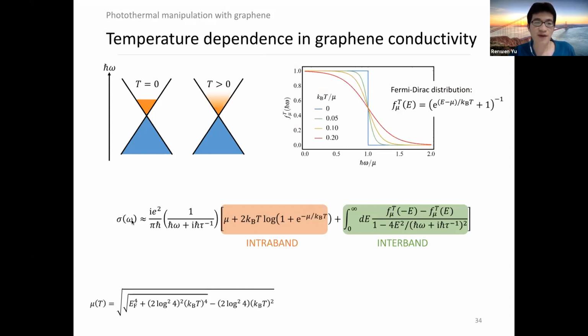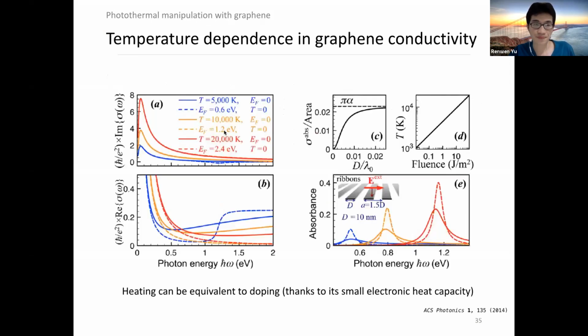Actually, we can express the optical conductivity of graphene in terms of its intraband and interband transitions. And both transitions actually are temperature sensitive, as you can see here. So when we just increase the temperature, it can provide a similar effect as doping. So heating can be equal to doping in this example. And if you look at the far-field response, we can see that the heated graphene and doped graphene can provide a very similar optical response in the far field.